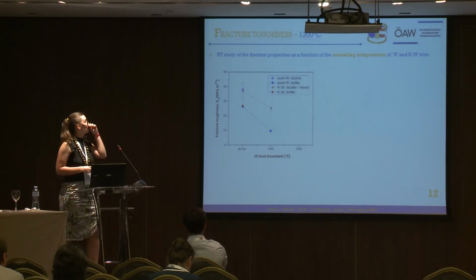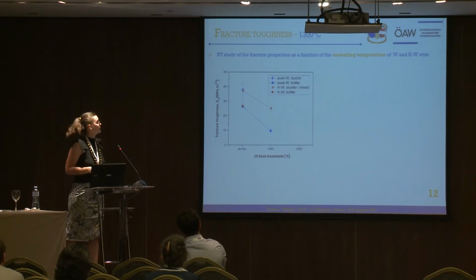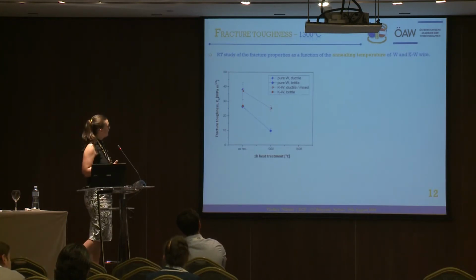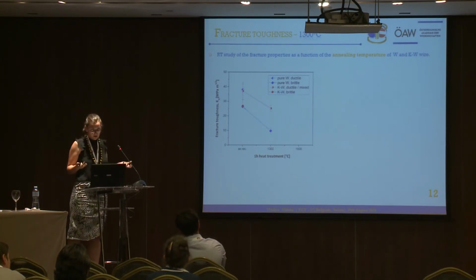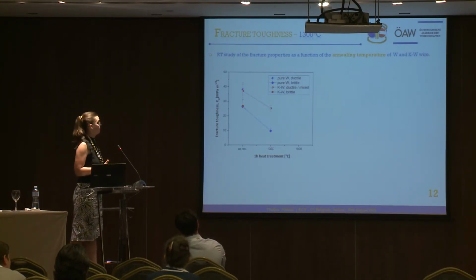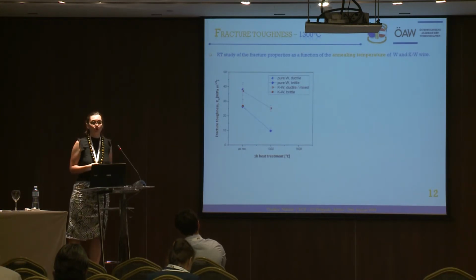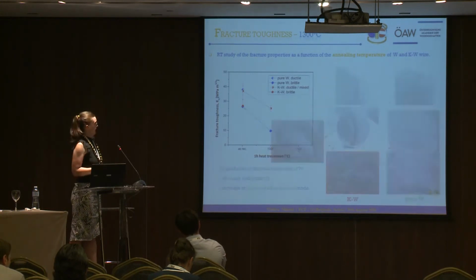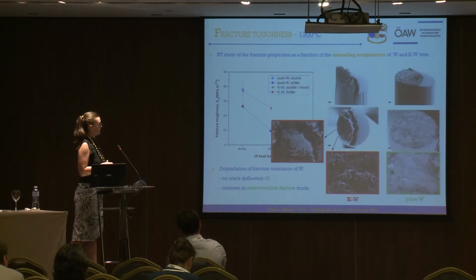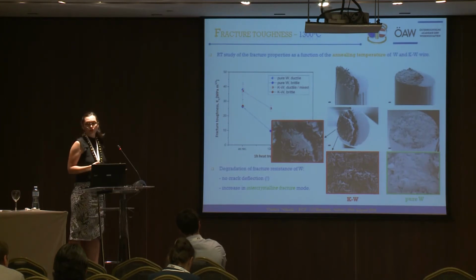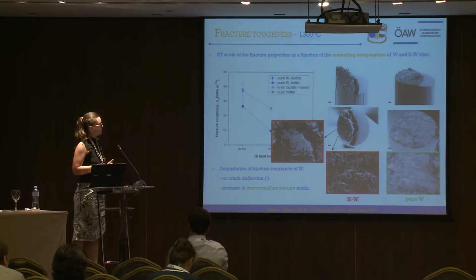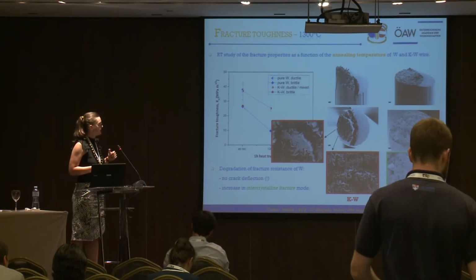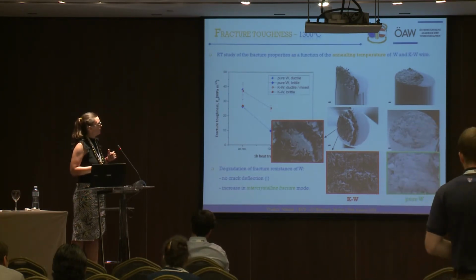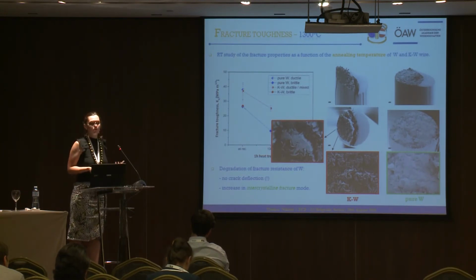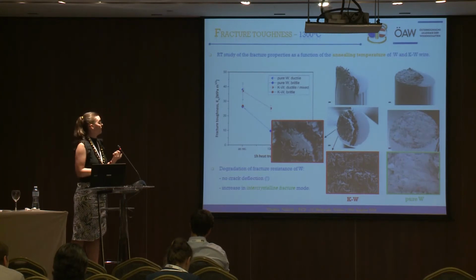Okay. So going now to the next set of samples, 1300 degrees C annealed samples. Looking at the toughness values, we can see that there is a decrease in toughness, with the effect being very pronounced for pure tungsten. So there is embrittlement by annealing, essentially. And if we now look at the fracture surfaces, on the left is the potassium doped one, we see very similar appearance as in the case of as received material. In some areas, there are roughly flat cleaved grains, but these areas, as you can see in this overall fracture surface, are very small. So we can consider this predominantly a ductile failure mode.